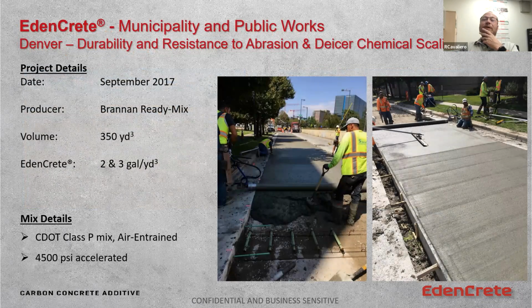Denver, City and County of Denver. They use EdenCrete for de-icer chemical scaling resistance. This is down on Speer Boulevard where Speer and Broadway and the Raceway come off to where Speer comes out of the tunnel when you're heading down towards Cherry Creek. We did 1 lane with 2 gallons per yard of EdenCrete and 1 lane with 3 gallons per yard. We just simply added it on top of the CDOT Class P mix.